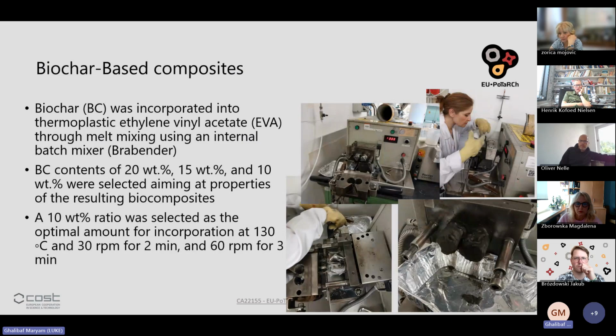And then about this biochar-based composite, which was the main activity I completed during my visit, the biochar was incorporated into the selected polymer, which was thermoplastic ethylene vinyl acetate, through the melt mixing blender. You can see in this picture. It was my first time working with this machine. That's why it was good and also challenging for me. But I obtained good experience in this field also.